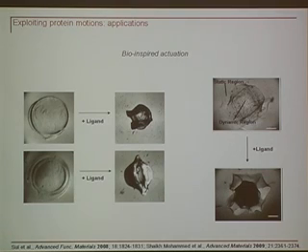So in terms of actuation, we've been able to develop materials by varying the local concentration of Calmodulin in a gel, by applying electric field, etc. Materials that can undergo anisotropic shifts in volume. So materials that bend, like this sort of hydrogel. Materials that collapse along an axis, like this kind of a hydrogel. And then what's potentially important for actuation is materials that have dynamic units that can do work on non-dynamic units.